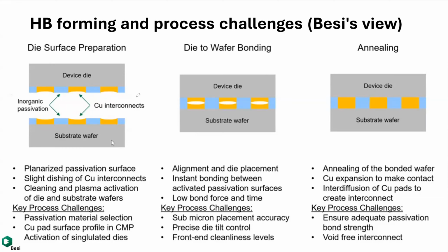And you want to have a shallow, a little bit concave, convex, concave interface between copper. So you will form some kind of small void. That's by nature. They don't really want that, but that's what happened after you CMP it as a local dishing. Is that a good thing or bad thing? Actually, it's not a bad thing, you know. Then you have a void, of course. Then later on, you're gonna anneal it off, right? With some high temperature, not too high a temperature. You don't want to kill the die, right? The die cannot put up with more than 400 degrees.